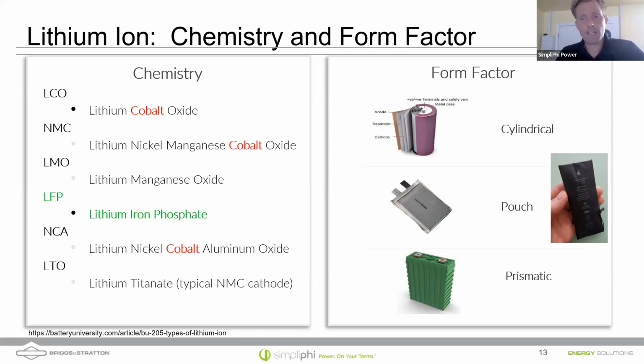and that plastic casing, especially with the geometries, ends up expanding and contracting more with time, with charge and discharge cycles. So when you charge and discharge a battery, it heats up, and that amount of heat causes thermal expansion. And if those batteries get too hot, that thermal expansion can cause separation of layers and other problems, breakdown of chemistry inside the batteries. And so prismatic cells don't last quite as long as cylindrical cells, but they tend to be a little bit cheaper.